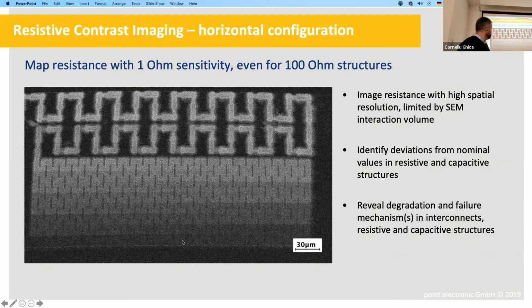And in this example, we have a meandering resistor built in a CMOS device. And you can see segments of this resistance, top layer, bottom layer, with a via in between. And this is meandering along as a way of building up more resistance. So this way, you can design and you can make a resistance of 100 ohms or 500 ohms or 1 kilohm and so on, just by having longer chains or by having more layers connected through wires. And we can see how the intensity of... we have one probe connecting at the beginning of this wire and one probe connected at the end of the wire. And we can see how the intensity of our RCI signal is going down as the resistance is building up. So it's a great technique to map resistance.